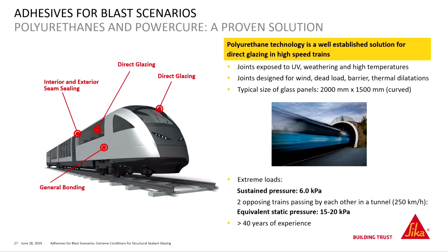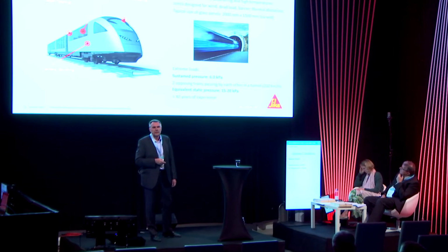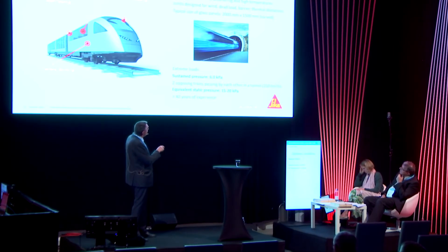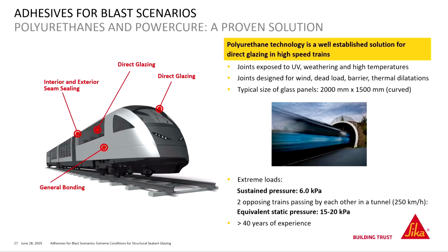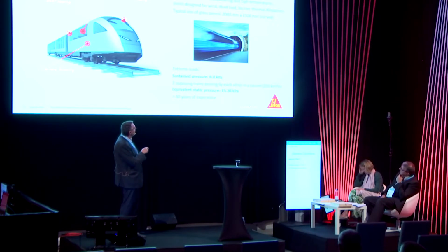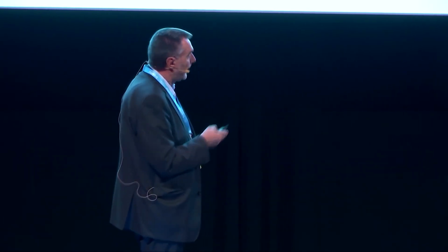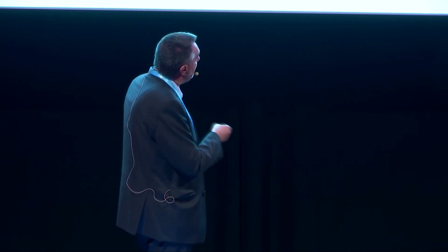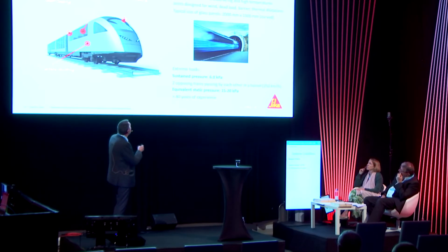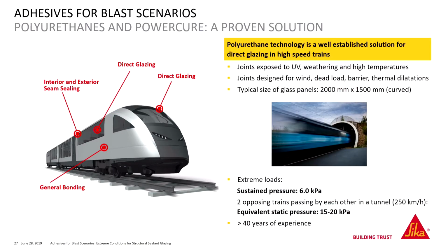When you look at the parameters in the train industry, the size of the glass panes here is 2 meter by 1 meter 50. That's very similar to a facade element. The wind loads, 6 kilopascal. In Europe, you don't reach it that much. In Asia, okay. But here, when two opposing trains are passing in the tunnel at the speed of 250 kilometers per hour, we talk about a static pressure of 15 to 20 kPa. This will never be met by wind loads in reality. And meanwhile, we have about 40 years of experience with polyurethane in the transportation industry, in trains, bus, trucks, ships, and so on.